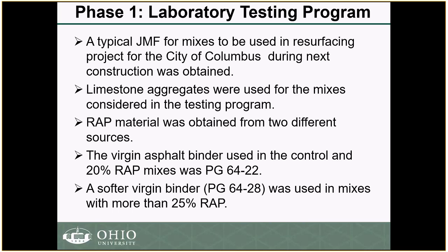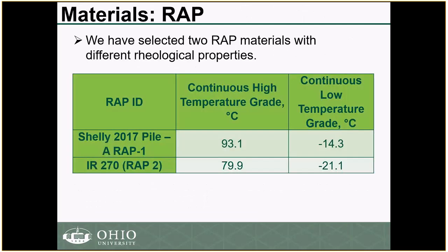We used a virgin asphalt binder in the control, which is a virgin asphalt mix, as well as the 20% RAP mix, that is PG64-22. That was the virgin asphalt binder used for those mixes. The other mixes, with more than 25% RAP, used a softer binder, a PG64-28. And this was based on testing of the binder.